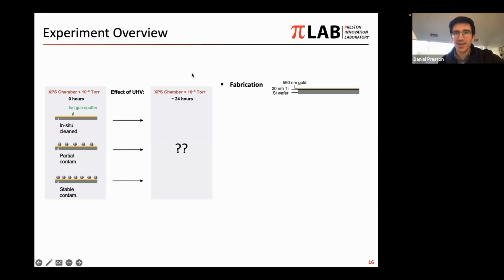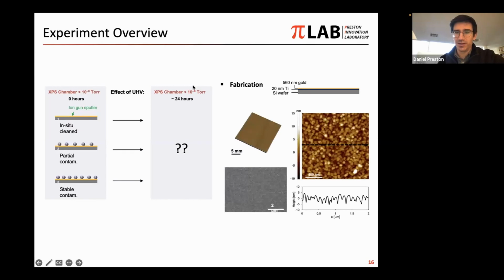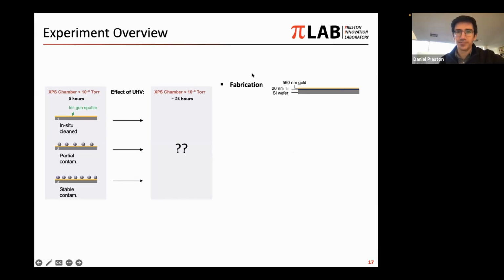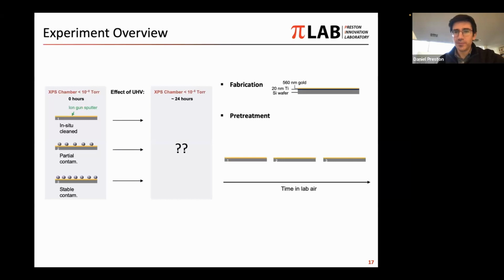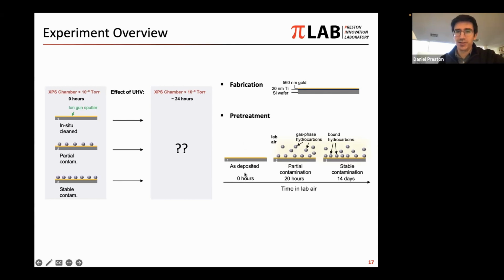What do we observe? And so we fabricated some surfaces that were flat and gold. We zoom in here and we can look at the surface morphology and find that the roughness is quite small. So we expect these nominally to be flat and nominally to be fully gold-coated surfaces. We pre-treated them. In this case, we have 3 different types of pre-treatments. First, we just take 0 hours in lab air after cleaning. That's not going to have much contamination, so as deposited here. And then if we let it sit in lab air for different periods of time, we might call these a partial contamination, not fully contaminated with hydrocarbons. And then maybe if we let it sit for much longer, it approaches a steady value in terms of the contamination.